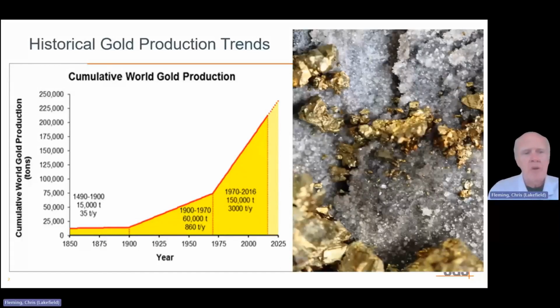And in that period, around 15,000 tons of gold was accumulated, which works out to a linear average of 35 tons per annum. Almost all of this gold was recovered by gravity separation, because that was the only technique that was known to man at that time. And the equipment they used was very crude. They had sluice boxes, panning machines of various design, but recovery efficiency was very low, typically less than 10%. So only the highest grade deposits could be found and processed.